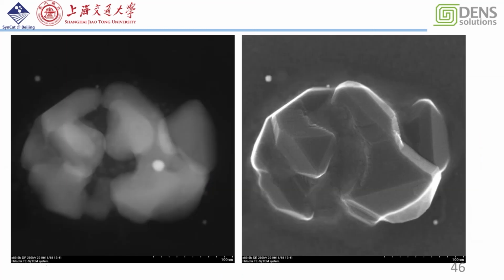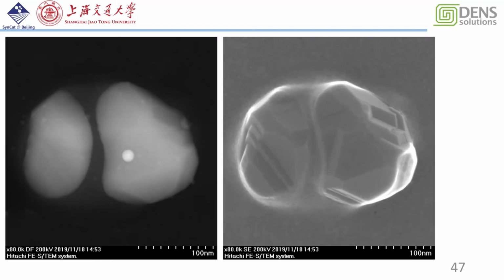So this is a good example to show how we found the position of the iron. Iron is not on the surface. It means that hydrogen can easily diffuse from the iron oxide into the bulk and reduce the iron oxide to the iron. It also suggests that the reduction process is not stopped by coverage of the iron blocking the diffusion of the iron oxide. And we checked different particles. We always found this big particle is inside, beneath the iron oxide. It's not always on the surface of the iron oxide.